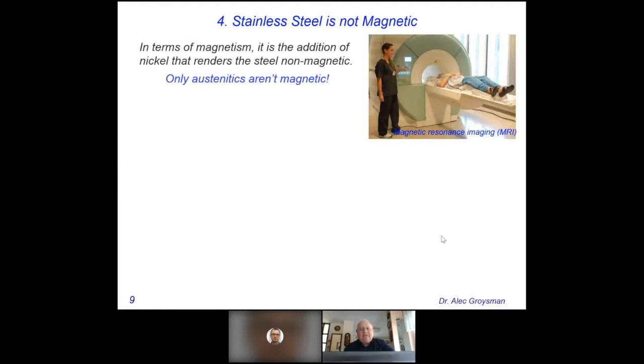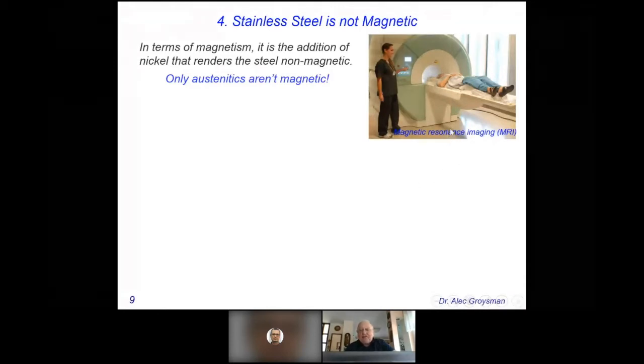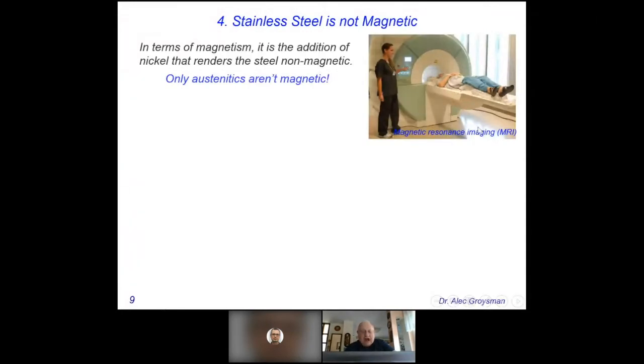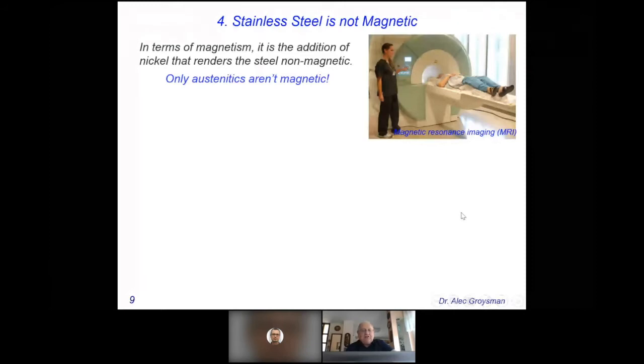But there are 5 types of stainless steels according to crystallographic structure. Only austenitic stainless steel that has not been work hardened is non-magnetic due to its nickel content. Austenitic stainless steels are used for non-magnetic applications, for example, mass spectrometer or magnetic resonance imaging, MRI. Other types of stainless steels are magnetic. Therefore, the use of a magnet can be applied only to decide if the steel is austenitic, and cannot be used to define ferritic, martensitic, duplex, and PH stainless steel.